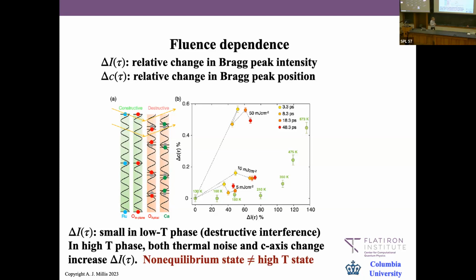However, if you heat the system up, then you get a lot of thermal fluctuations. You get a Debye-Waller factor that messes up the destructive interference, so the peak amplitude goes up. So this is a plot of the change in peak position, interpreted as a change in c-axis lattice parameter, versus the change in peak intensity.